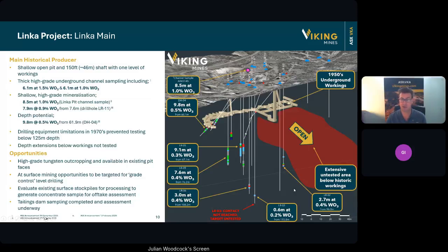Now, the couple of deepest holes that were drilled at the project, which is LR03 here, as well as LR04, these two holes didn't reach the contact. They were restricted by the limitations of the equipment that was being used in the 1970s. They just didn't have enough air to get those rotary holes to depth. And so that prevented them from testing the contact. And this is an area where we see an opportunity and an area where we'll be undertaking drilling in our maiden drill program.